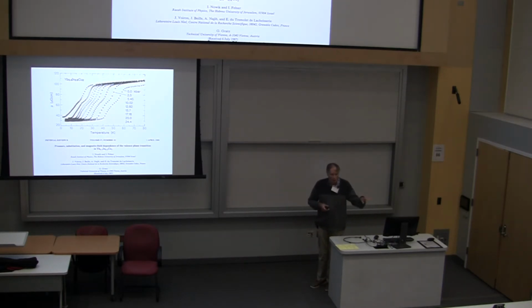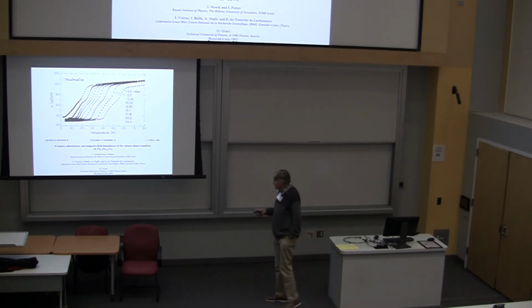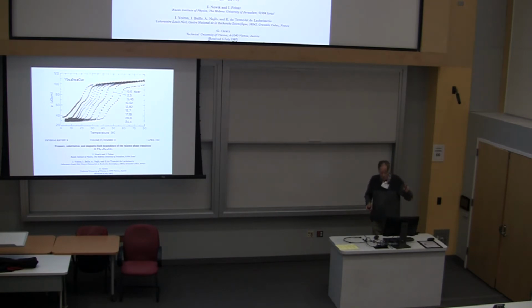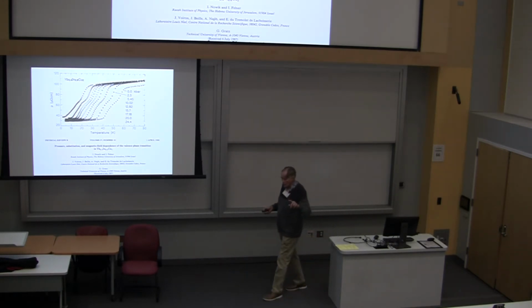But they're all chemically very similar, and that's of course why it's wonderful to work with the rare earths, because you can substitute one for the other and do all kinds of comparative experiments. But when this work came out, it occurred to me I'd done some work with these lattice phases, and as I say, the rare earth, in other words, the ytterbium plus indium, there are these two face-centered cubic lattices, and so you could put a different atom, perhaps, on one of those cubic lattices.